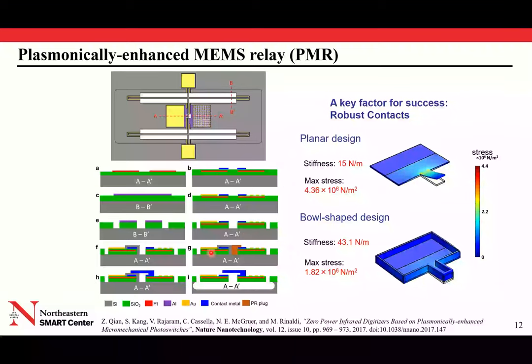Only a few things that we did interesting in terms of processing here is that instead of using a conventional planar design tip, and we will see this in all the papers that we published from my group, we use this sort of bowl-shaped design. That was a way for us to build a stiff enough tip for this structure without going through a more complex fabrication process. So it's a very well-controlled liftoff process of a platinum layer that allows us to build this pretty stiff tip using a relatively thin metal layer. So that's one of the tricks we used. Certainly in commercial foundries, there are other ways to build tips, as you might know.